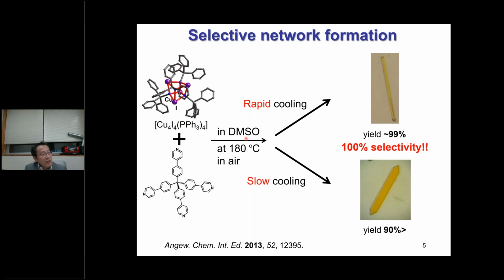If you mix together in DMSO at 180 degrees, these materials can be dissolved. Then when you cool down rapidly, you can get the kinetic product, the kinetic network. The yield is quite high, almost 100%. On the other hand, in the slow cooling case, you can generate a thermodynamic network. So surprisingly, you can selectively prepare this material. This is supposed to be a kinetic product. However, this one is stable enough.